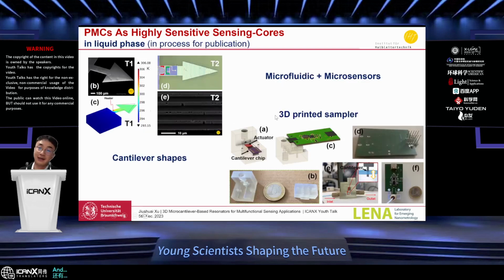And as the two presenters before today did also very impressive work when introducing the microbubbles, we did also some trials of the application of these sensors in micro liquid. So the sensor has been machined with these micro fins, as for the humidity sensing, and the micro liquid can go through the microfins, and the adsorption can happen.